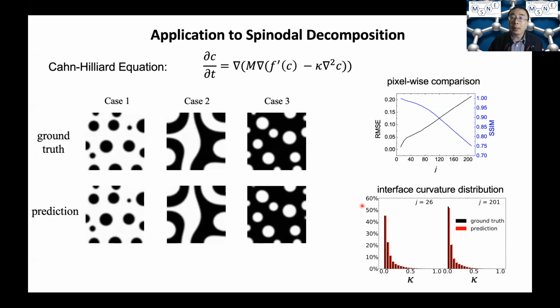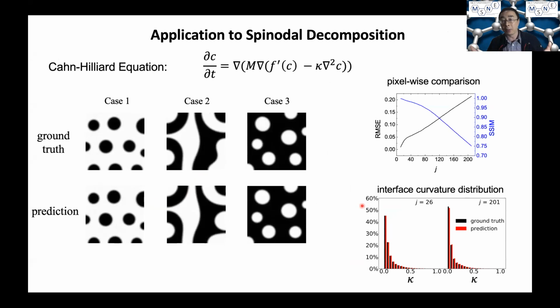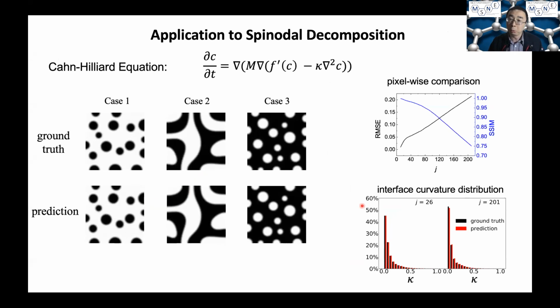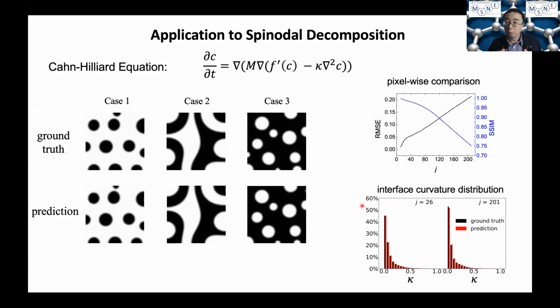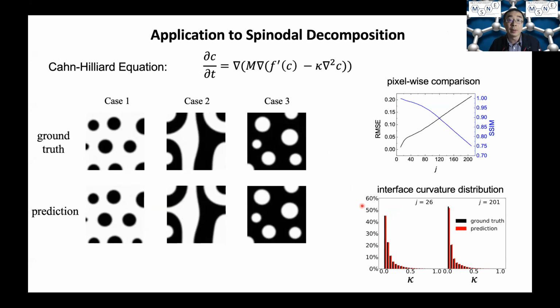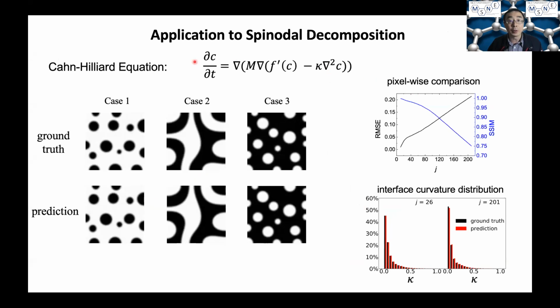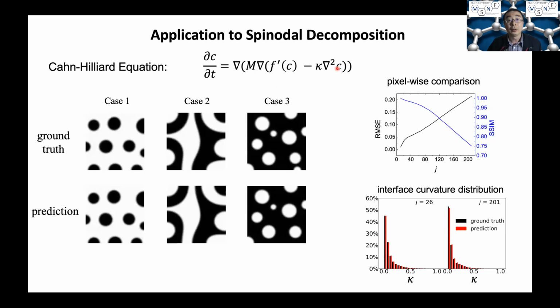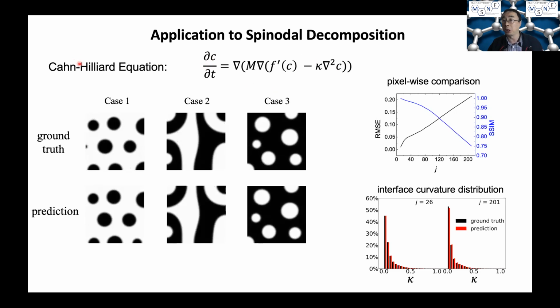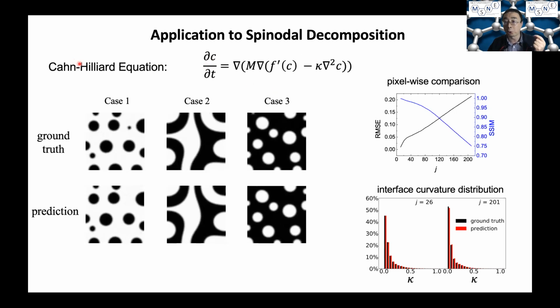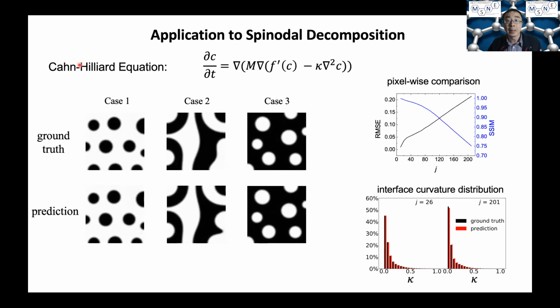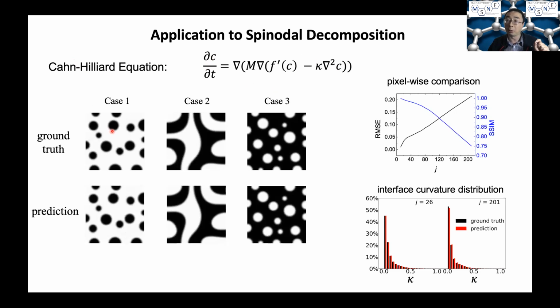Right? And we also applied the RNN model to study some other well-known microstructure evolution phenomena. So one is spinodal decomposition, which Fei presented in his talk, which is the spontaneous phase separation process in unstable solid solution systems. And traditionally, spinodal decomposition was simulated by the Cahn-Hilliard equation, which is a nonlinear fourth-order equation. So here we use the Cahn-Hilliard equation to generate simulation data, and then train the RNN model based on such data. And again, we see the performance is comparable to the grain growth examples.